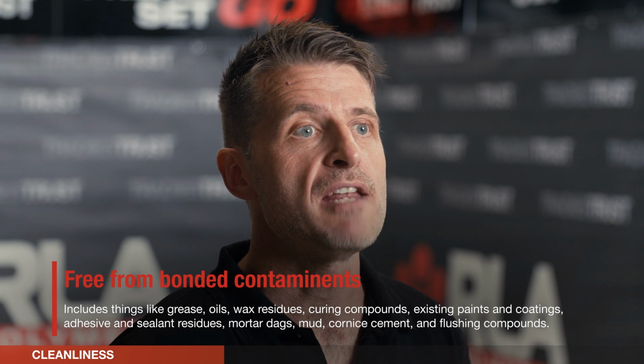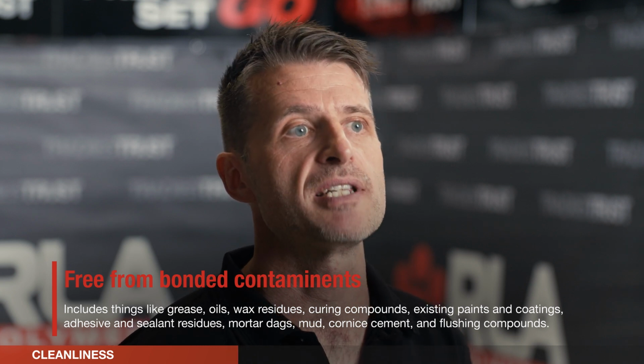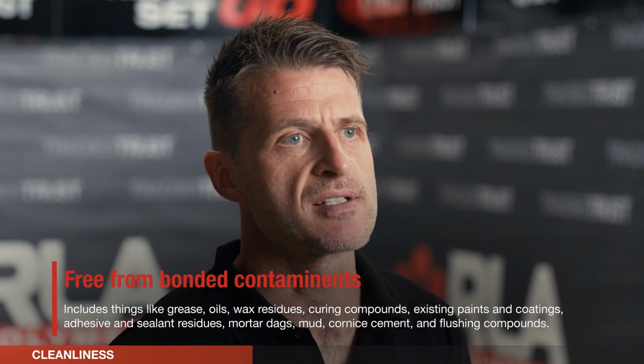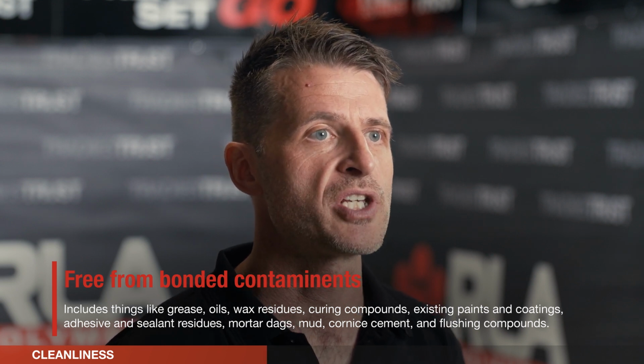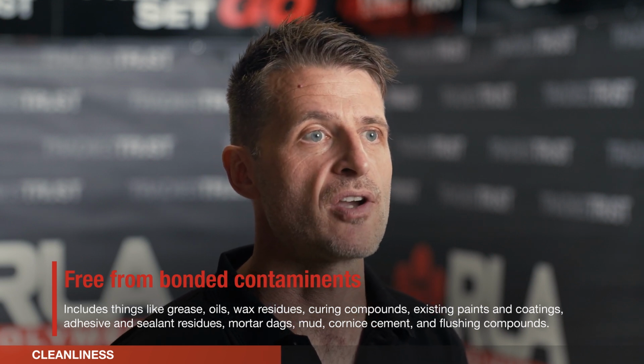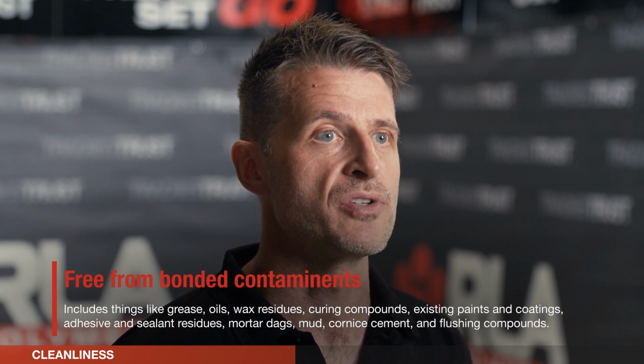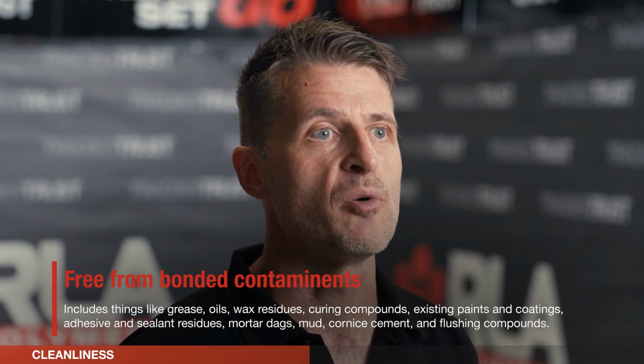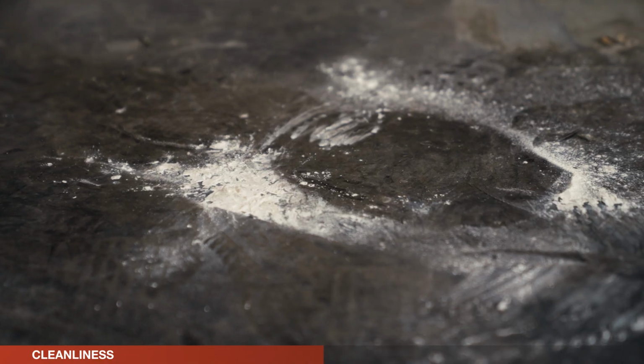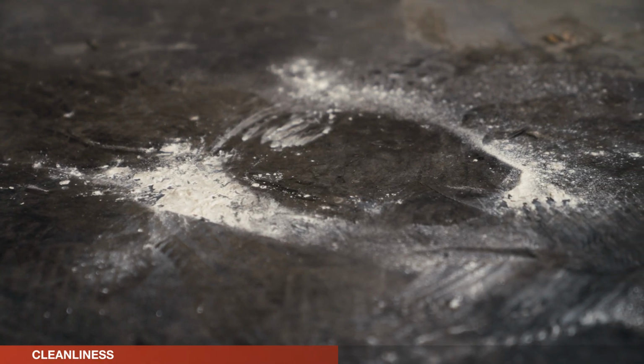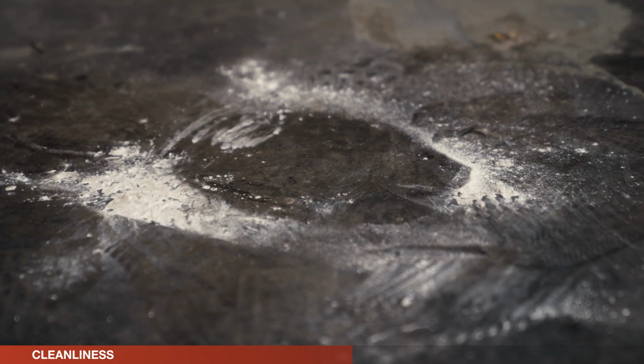Next, we ensure the surface is free from bonded contaminants, meaning any foreign material that may be bonded to but not actually part of the substrate. And this includes things like grease, oils, wax residues, curing compounds, existing paint and coatings, adhesives and sealant residues, cornice cement and other compounds, to name a few. Anything that can be considered a bond breaker that prevents the applied system from adhering directly to the surface. Now, these contaminants will require a bit more effort to clean by either using chemicals such as degreasers for grease and oils, to manual scrapers, wire brushing, and mechanical grinding.